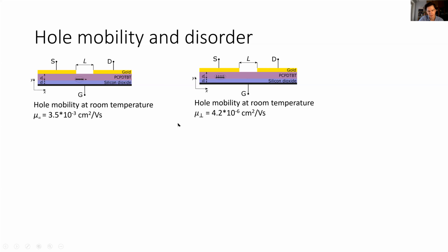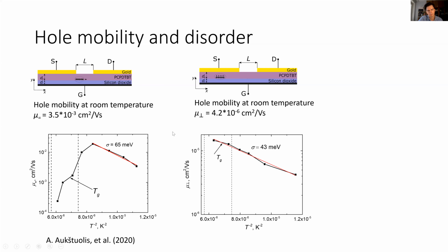This kind of non-linear behavior was not a surprise, but an interesting result. So we dug further and did temperature measurements. We measured through the whole heating session. We started at room temperature and heated, and at each point we measured the mobility in both cases, because we can easily switch between the methods since the setup is quite similar.